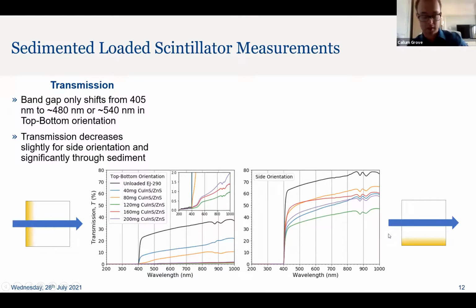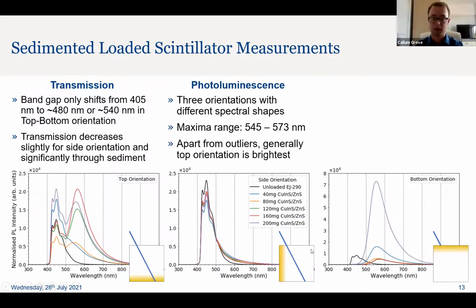For the sedimented loaded scintillators, the transmission dropped off significantly for the top and bottom orientation, so through the sedimented layer, and you have no plastic absorption, but you have this quantum dot absorption only, so that's doing the primary absorption. And then the side orientation through the bulk medium dropped off slightly, indicating some quantum dots, but the shape is not significant.